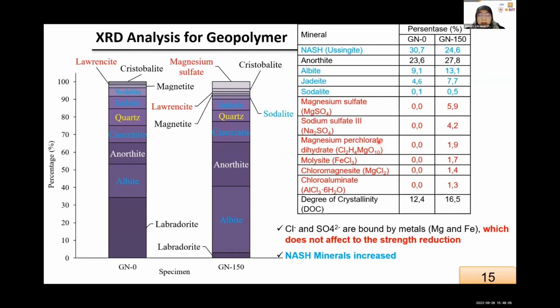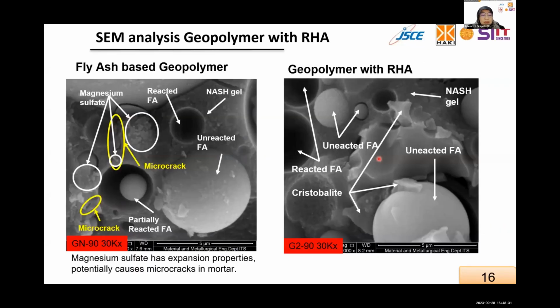Chloride is bound by iron, alumina and magnesium, while the sulfate is immobilized in the formation of magnesium sulfate and sodium sulfate. However, the geopolymeric gels remain non-threatening. It's still okay, as there is an absence of product decomposition. We cannot see any decomposition product here. And this is the SEM analysis. Magnesium sulfate here is observed to be encapsulated within the geopolymers.